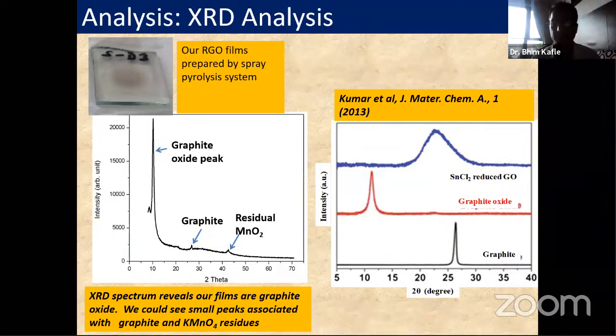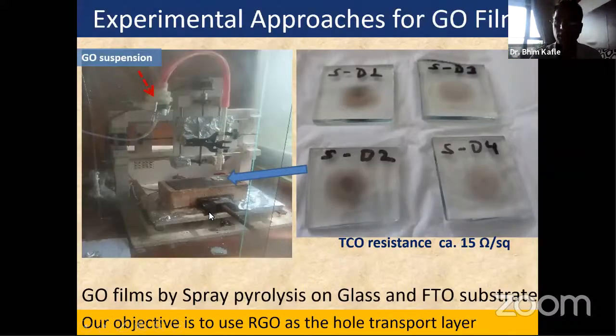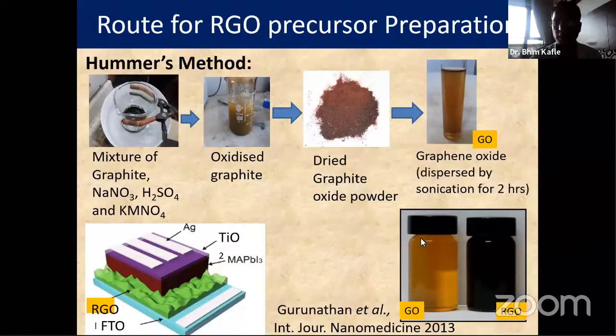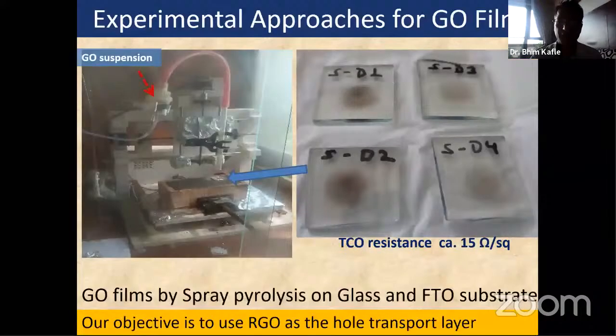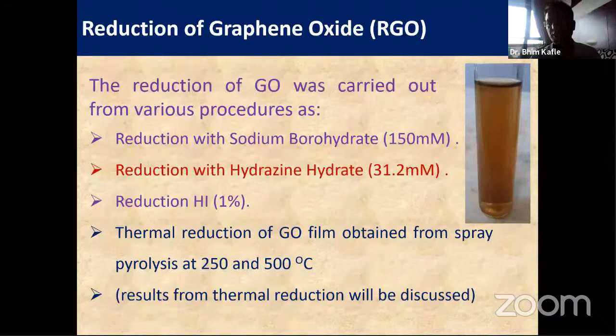So it's showing the property of graphite oxide, and it also shows a few percent, very few, of graphite contamination. I mean, it was not leached out completely, since graphite powder was then processed chemically. So there is a very small percent of impurity. Maybe this is why our sample looks slightly blackish compared to other reported work. And then eventually after that we reduced our graphene oxide solution by various methods.